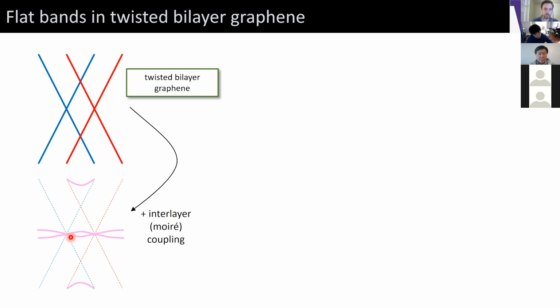Now there's a special symmetry of twisted bilayer graphene called C2 symmetry, which is basically 180-degree rotation symmetry. And this is equivalent to exchanging the valleys within a single layer of the monolayer graphene. And because those valleys are identical, the symmetry is respected. And the symmetry is actually responsible for protecting Dirac crossings at zero energy in the band structure of twisted bilayer graphene. So we essentially have a single tuning knob from the twist angle to be able to control how flat these bands are, by considering this kind of geometric ratio between their offset in momentum space and how strong the hybridization is that induces a gap at full filling of these Moiré subbands.